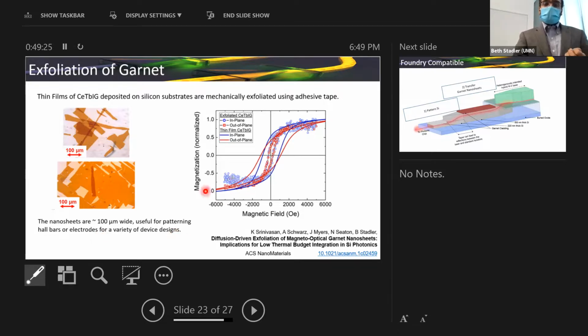Looking at the magnetization characteristics through VSM measurements, we see that the saturation magnetization is quite comparable to its thin film counterpart on silicon, attached and intact. Although the coercivity reduces, that's just a consequence of the exfoliated nanosheets losing their magnetoelastic anisotropy.